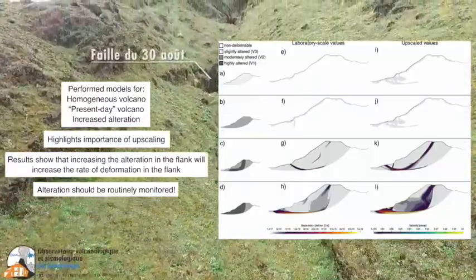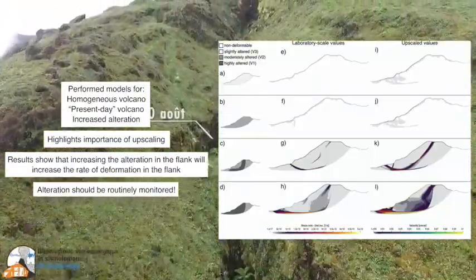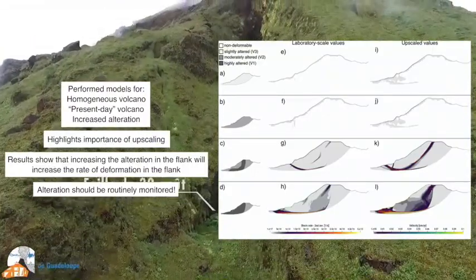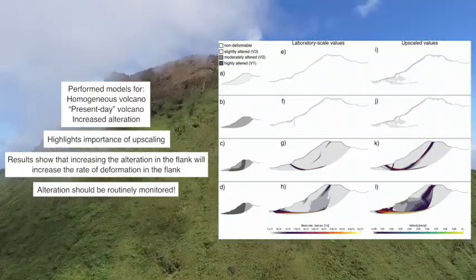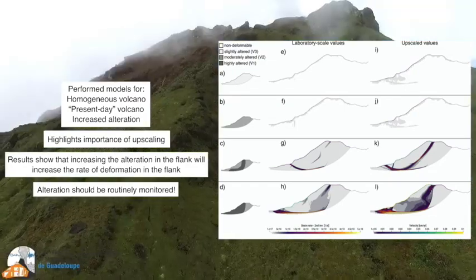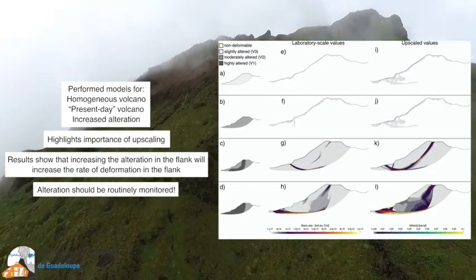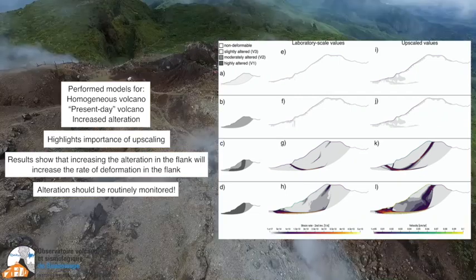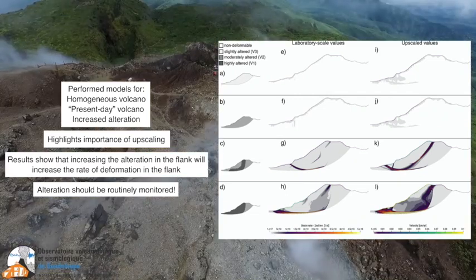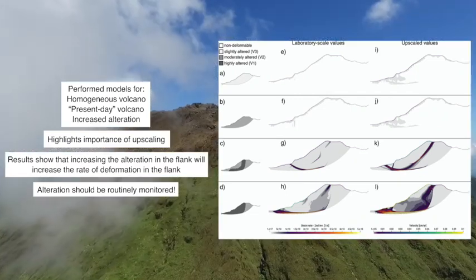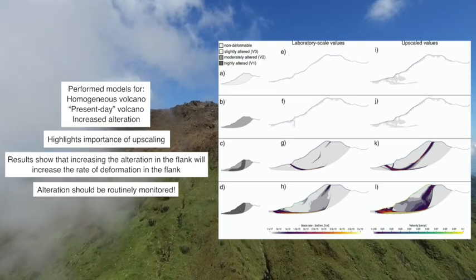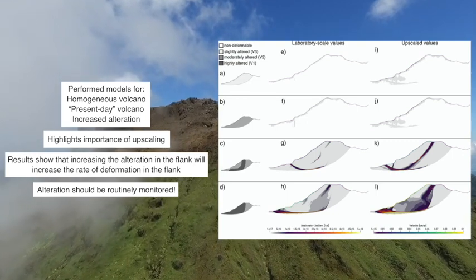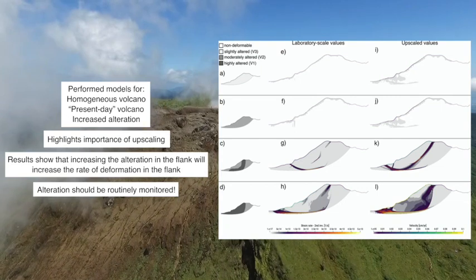When we introduce the highly altered zone, guided by the recent geophysical data, we can see that a high slip strain rate zone appears that results in the sliding of the southern flank. If we artificially increase the size of this hydrothermally altered zone, the bottommost diagram, we can see that the strain rate within the flank is much increased.